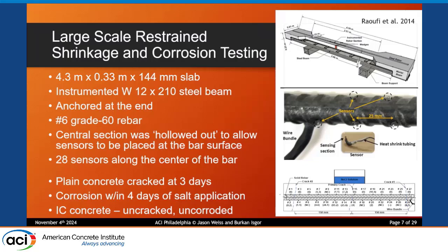Now, to demonstrate why this is so important, what we've done here is we've instrumented a large restrained slab. So this slab is about 15 feet long. It's got a reinforcing bar that goes through it. And if you get up close, really close to this, what you'll notice is we've actually drilled holes through the reinforcing bar and put little tiny probes along the length of the bar. Because what we want to figure out is when it starts to crack, how much of the bar actually starts to corrode. Because there's an argument that's put out by some people that says, well, the crack is only a little tiny piece of the bar. It's not that important. Don't worry so much about cracks.